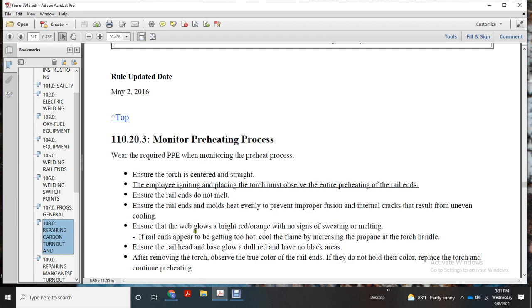Ensure the web glows bright red-orange with no sign of sweating or melting. If the rail end is getting too hot, cool the flame down by adjusting the propane at the torch handle. Ensure the rail head and base glow dull red and have no black area. After removing the torch, observe the true color of the rail ends.